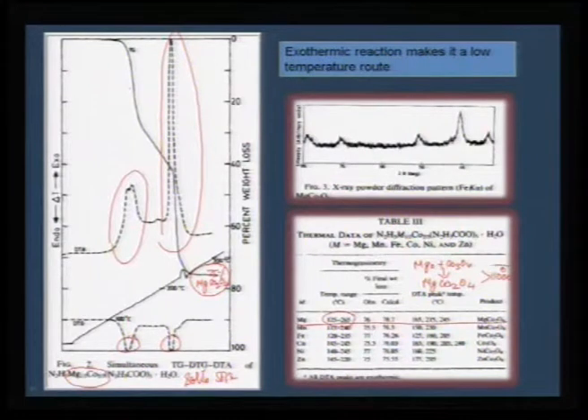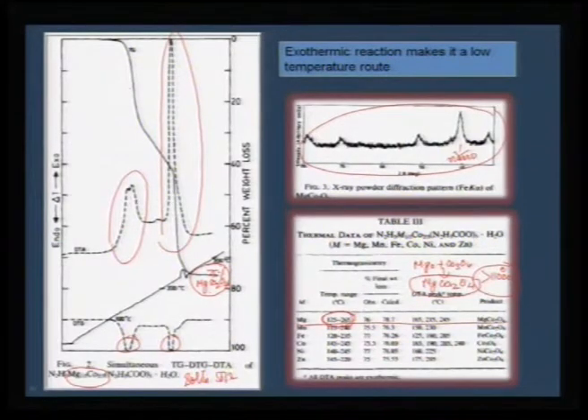You need this much of thermodynamic requirement for this final phase to form, whereas in the solid solution precursor route, you are able to prepare the same compound at a record temperature of 265 or 300 maximum, let us say. So, at 300 degree C, if you can prepare such a spinel compound, then the compound has to be highly reactive, and that is what we see from this X-ray pattern. The X-ray pattern clearly shows broad peaks indicating that they are nano in size. Because they are nano in size, they will be very, very reactive.